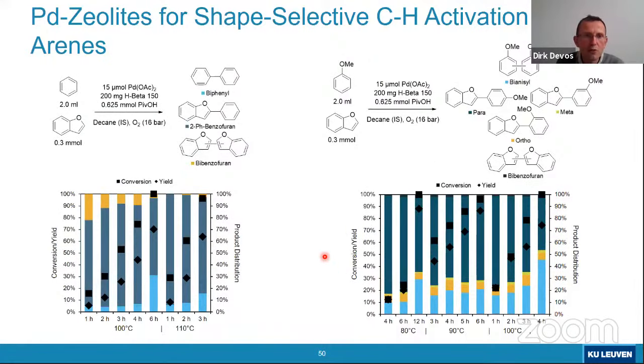This holds not only for this coupling of benzofuran with toluene, but also the reaction of benzofuran and benzene is already quite successful. We see that again, we make a lot of the heterocoupled product, which is this 2-phenylbenzofuran, here in darker blue, and also with the coupling of anisole and benzofuran, we have seen some quite interesting results with the beta pivalic acid system.